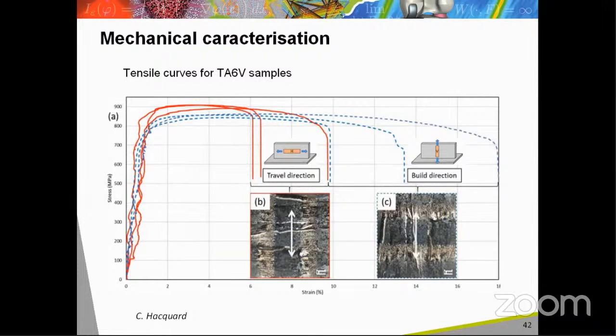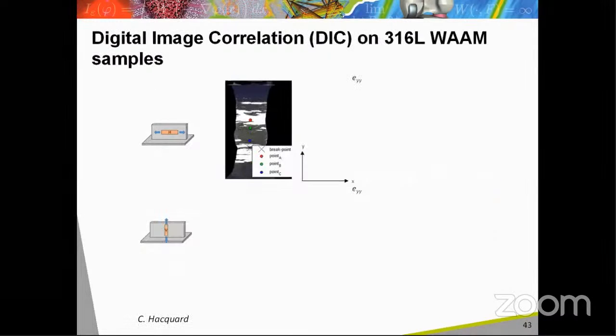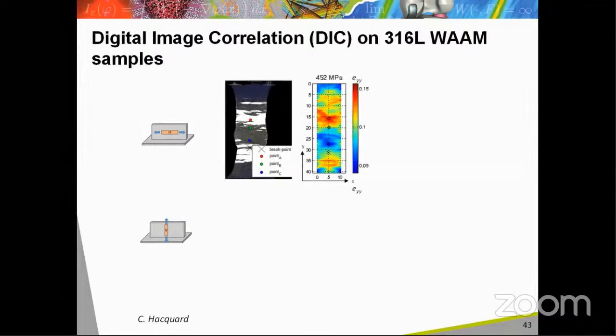In order to better understand the mechanical behavior of such samples, a digital image correlation method can be used. This technique allows to compare the mechanical behavior of the various areas of a heterogeneous sample by following the strain distribution on the sample surface. This slide illustrates the results of strain measurements by DIC method on samples of 316L stainless steel obtained by the WAAM process. One can see on the strain map that the strain varies on the samples due to the